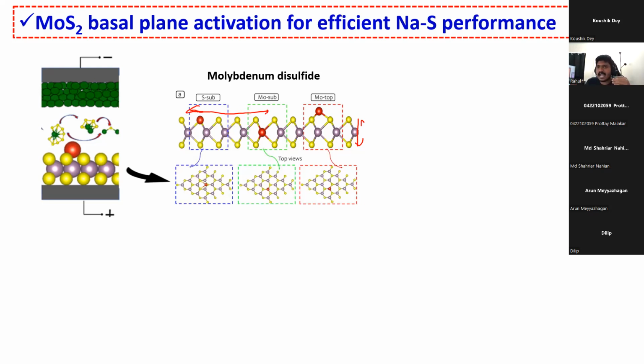So in order to activate the basal plane in the molybdenum disulfide, we actually doped the single atom catalyst at three favorable sites. One is sulfur substitution site. This is sulfur. We substituted on sulfur. And another is molybdenum substitution site. We basically substituted on molybdenum with the transition metal. And another is molybdenum top site. This is molybdenum top site.